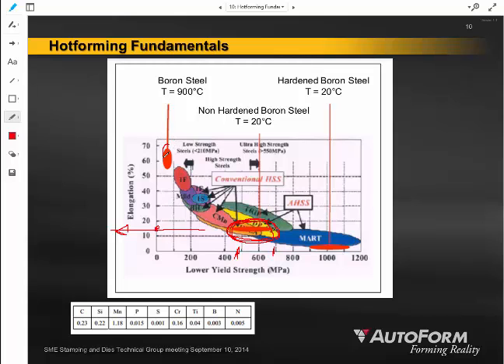However, when you heat these materials to 900 degrees Celsius, that material now becomes highly deformable, and it deforms quite well at these high temperatures, and now you can see 50 to 60% elongation of that material inside of the tool. And that's pretty good. That means that we can form even more complex shapes than we normally would use interstitial free or extra deep draw quality to form without causing a fracture or a failure in the material.